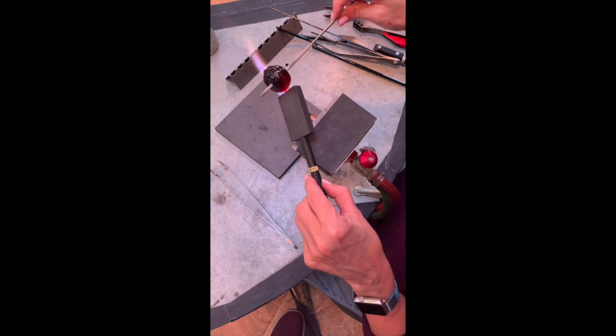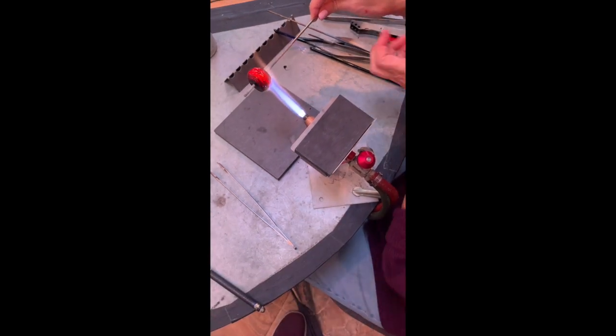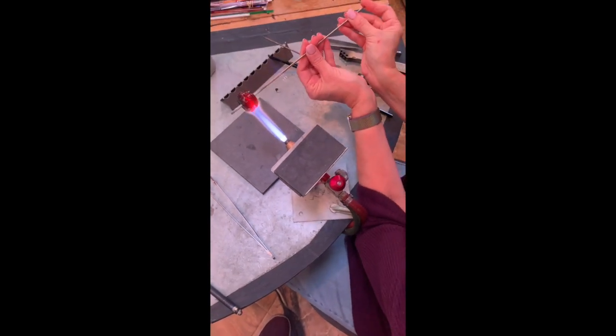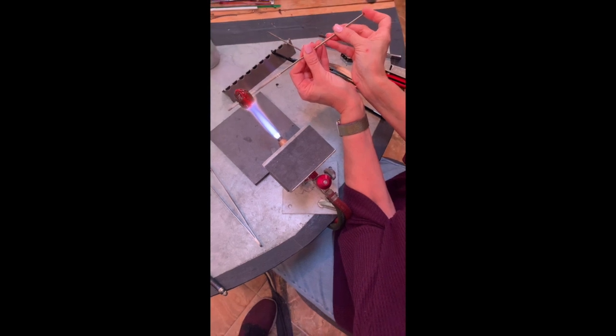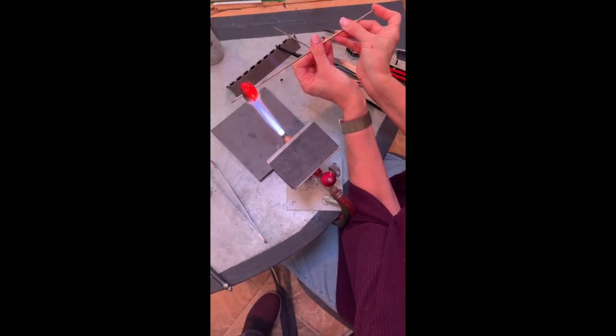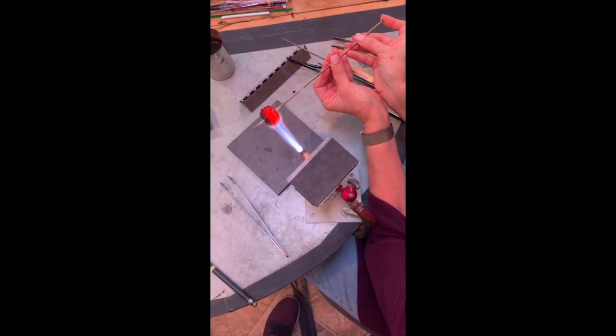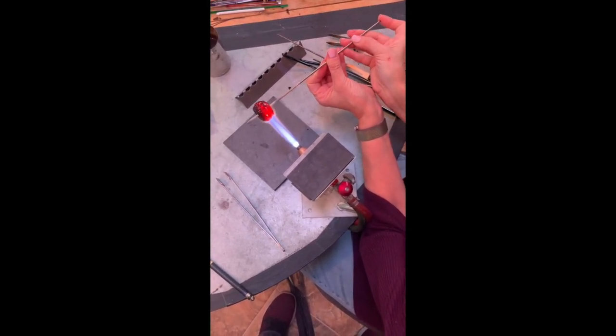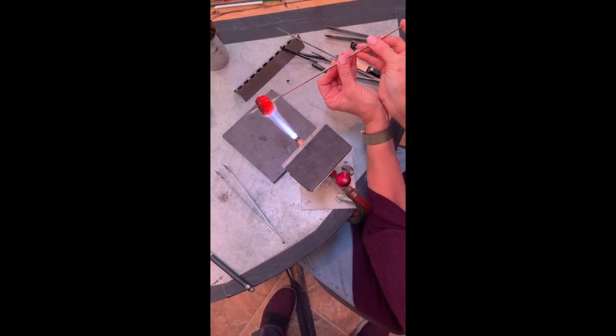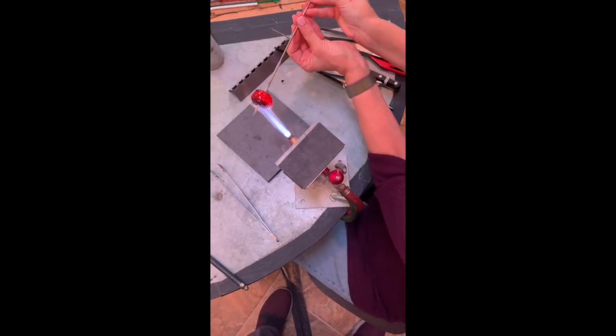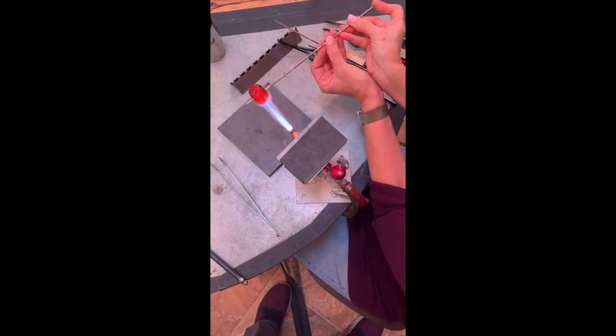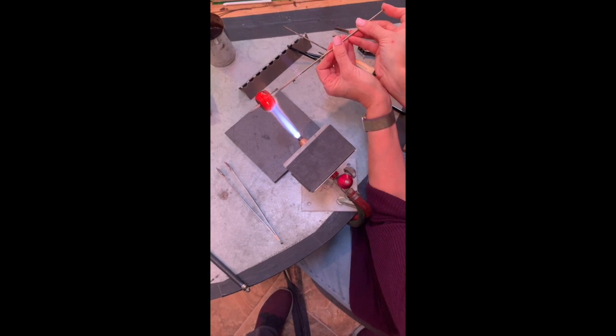what I'm going to do is I'm going to make sure to keep a finger or my palm over the open end of the mandrel. That way the bead cannot collapse and force all the hot air out the open end of the tube. And basically I will keep my finger over the open end of the tube until I put this bead mandrel into my mouth to inflate it.